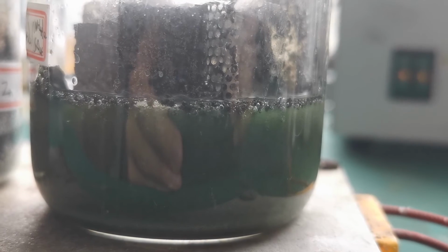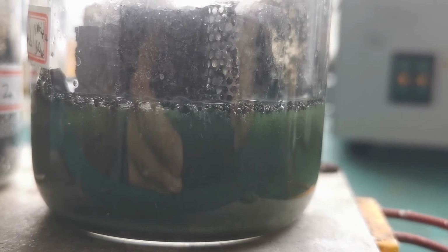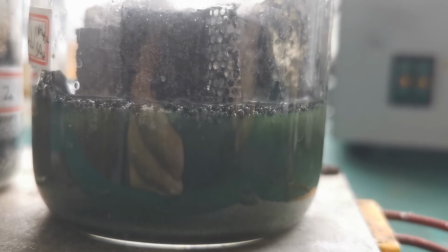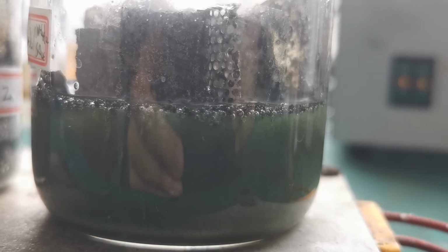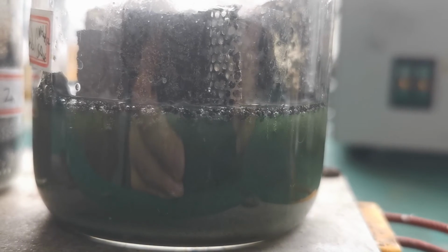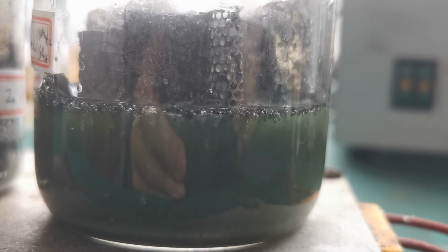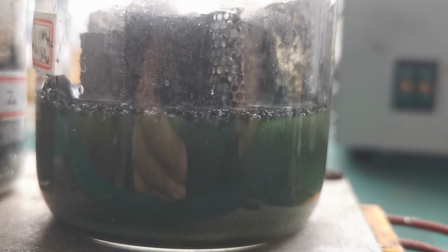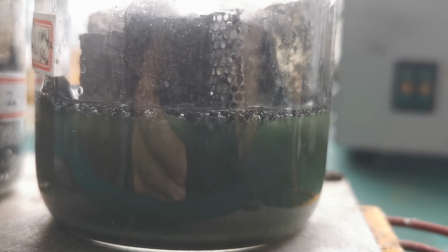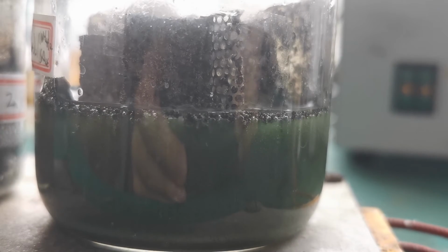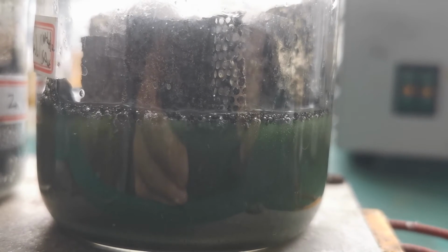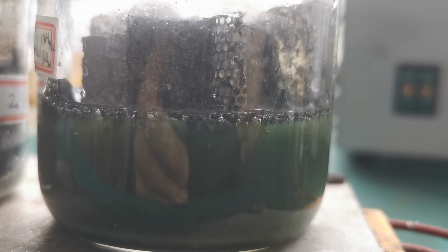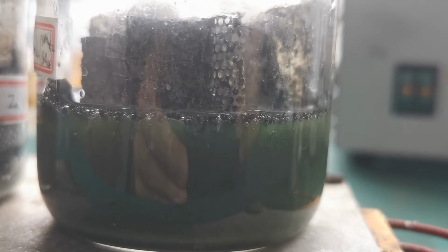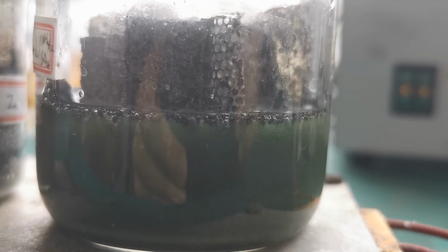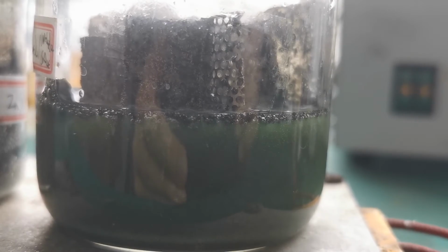There are still a bunch of black nickel hydroxide remaining, so I heated the acid again to completely dissolve them. The solution already gained a very deep green color due to the nickel ions, and if you look closely at the bottom of the beaker, there are some precipitates that are lighter in color. This is the lanthanide sulfate formed in the reaction, which crashed out due to its small solubility in boiling water. It seems a lot, but actually isn't a very big amount, so I don't think it is worth recovering unless you're recycling batteries on a very large scale.